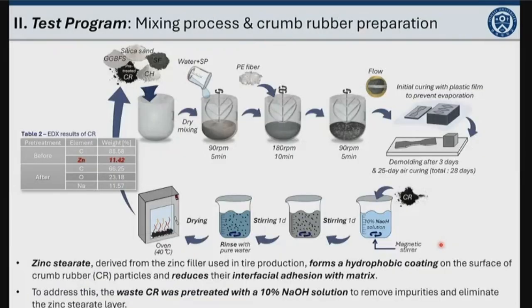This is the mixing process and the pre-treatment of the crumb rubber. The waste crumb rubber contains stearate, which originates from the zinc-based fillers used in tire production. Due to its hydrophobic nature, zinc stearate weakens the interfacial bonding with the matrix.